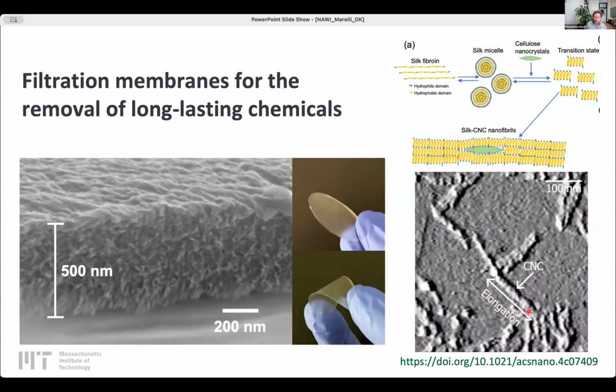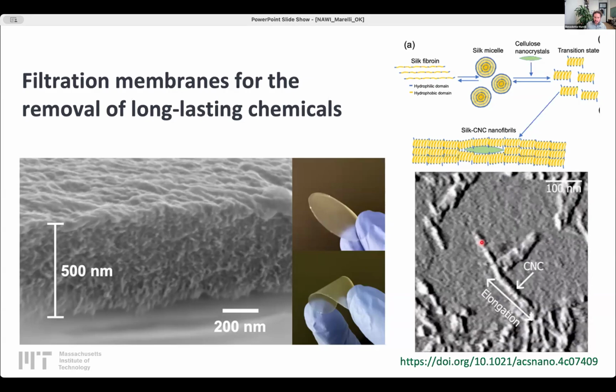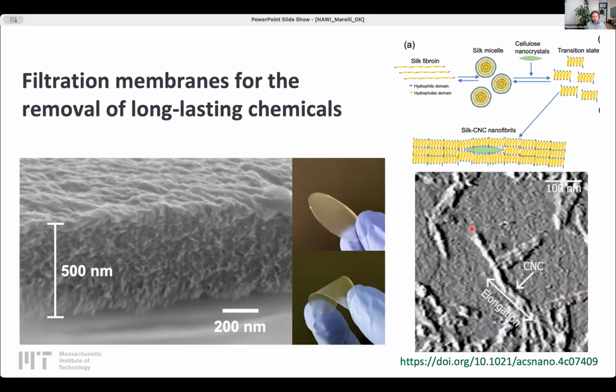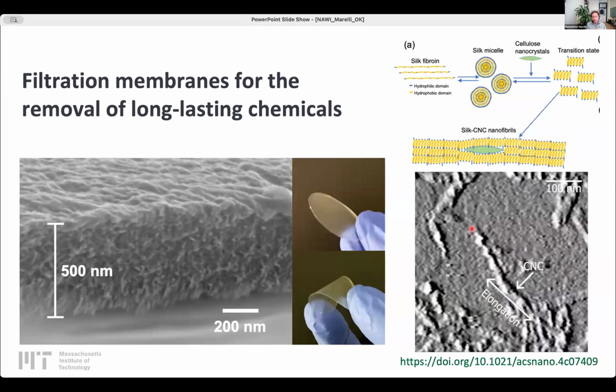In this case, the CNC templates the growth of silk in nanofibrillar matrices that are highly ordered. The big advantage of using the CNC is that the CNC can be functionalized into positively charged nano whiskers that can be designed to electrostatically interact with PFAS, as Aristide told us before. Electrostatic and hydrophobic interactions are key for